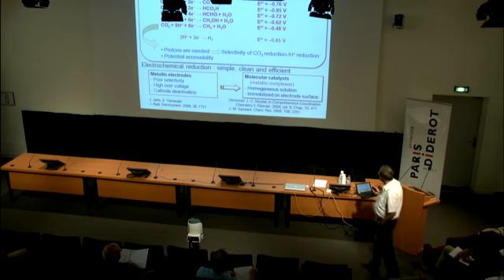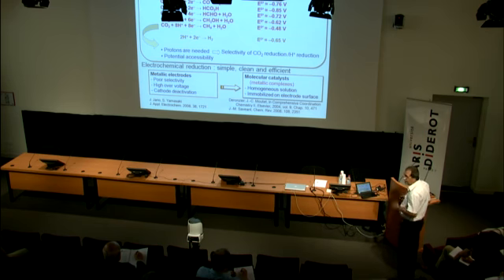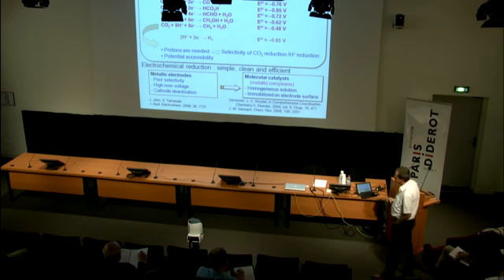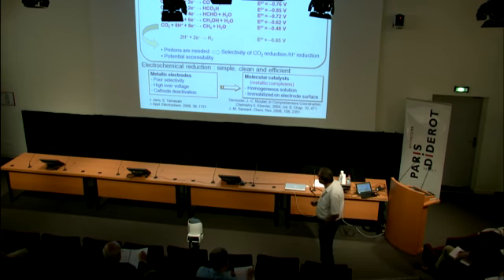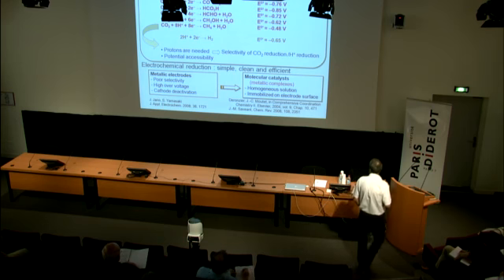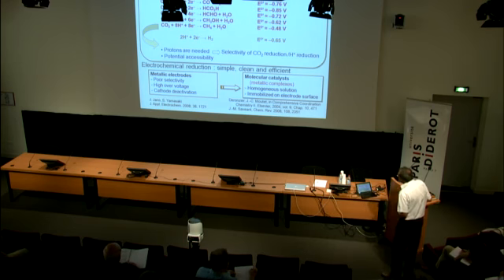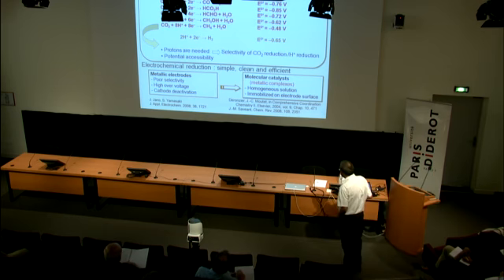methane. But don't forget that in parallel, you have to avoid the direct reduction of protons. Look at the difference of potential here. It's, of course, thermodynamic. And as you can see, the conditions to use a convenient process to reduce CO2 are: protons are needed, selectivity of CO2 reduction versus proton reduction, and more importantly, potential accessibility.